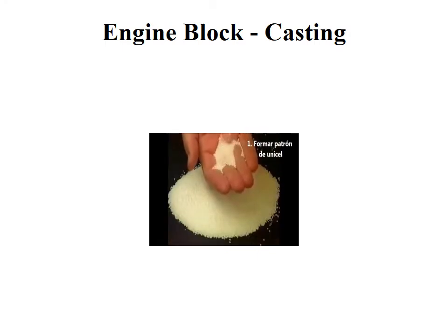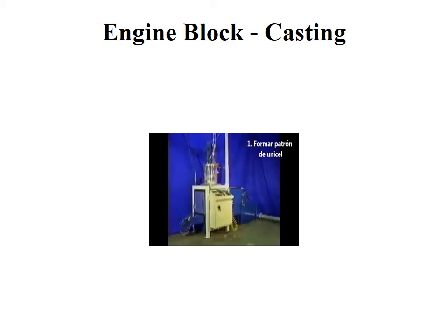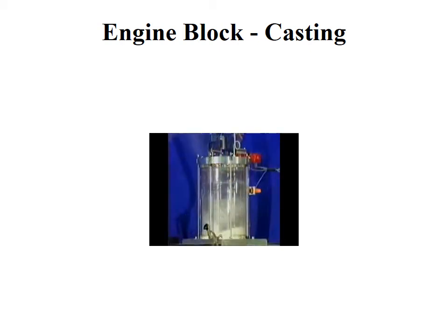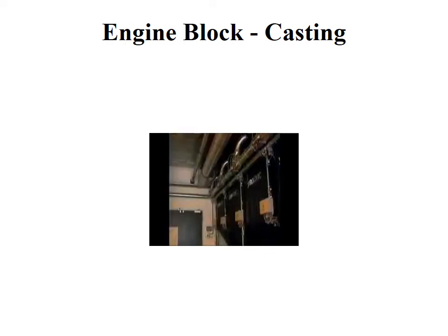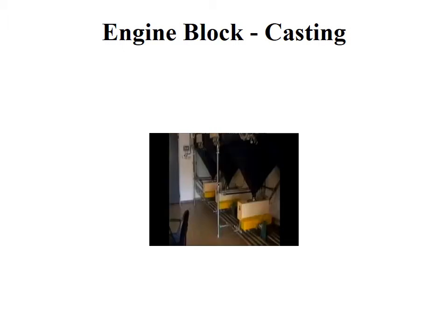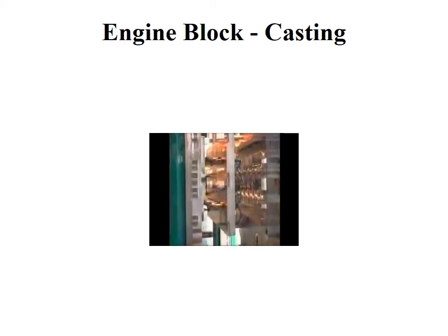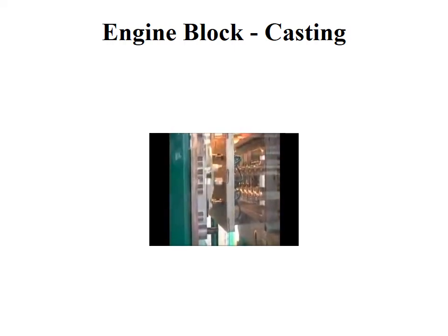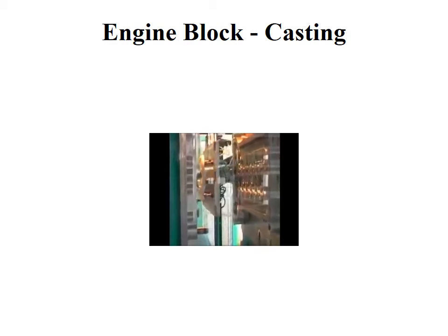The beads as purchased have a cellular structure and contain a gas or blowing agent, usually pentane. In a pre-expander, steam is used to heat the beads, softening the polymer and expanding the gas. Control of density and bead distribution is critical in this operation. After pre-expansion, the beads must be stored for stabilization before use in molding. A distribution system delivers beads from storage to the molding machines. Tooling mounted in a molding machine provides a cavity in the shape of the casting or a portion of the casting.